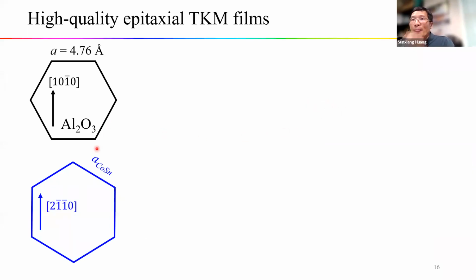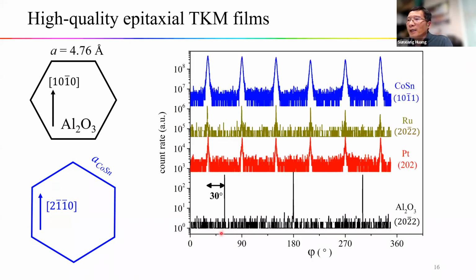As discussed earlier, to grow epitaxial TKM film on this substrate, we need this sort of 30-degree orientation for the aluminum oxide (001). So this is confirmed by the in-plane phi scan for the substrate as well as the buffer and the films. So clearly, the 30-degree offset is observed in this phi scan.